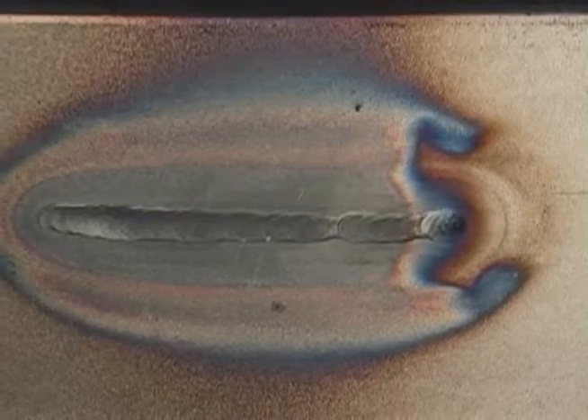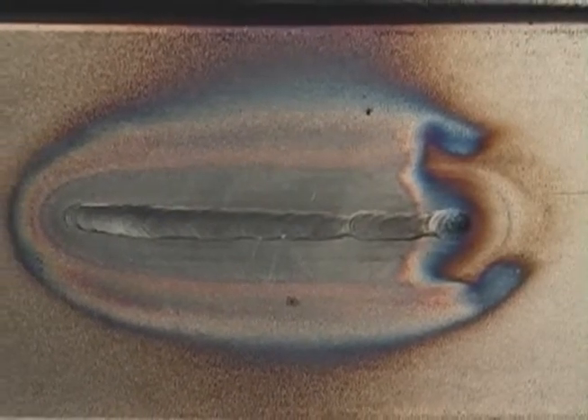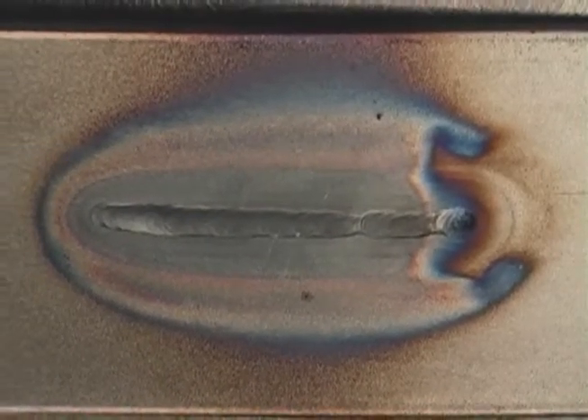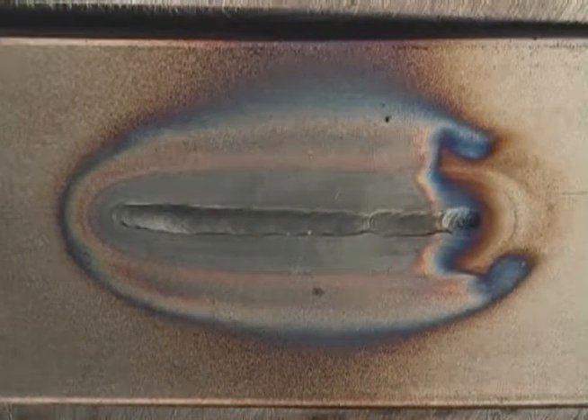The shield gas continues to flow, protecting the weld from the atmosphere, preventing a color change. If we made this weld in a purge chamber, which is a chamber filled completely with argon, the weld would not change color. Mild steel is not a reactive material like titanium or Inconel, and once the molten puddle solidifies, further cooling without the protection of the shielding gas will not affect the quality of the weld.